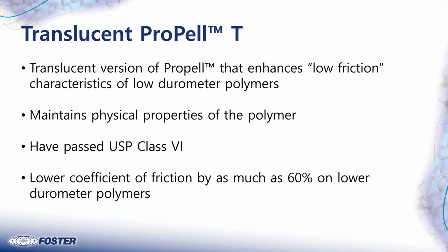Well, you could reinforce the polymer, just as in injection molding applications, they load it up with carbon fiber or glass fiber. Very difficult to do that in extrusion because the wall thickness is so thin, the fibers stick out, you just wouldn't be able to extrude it.